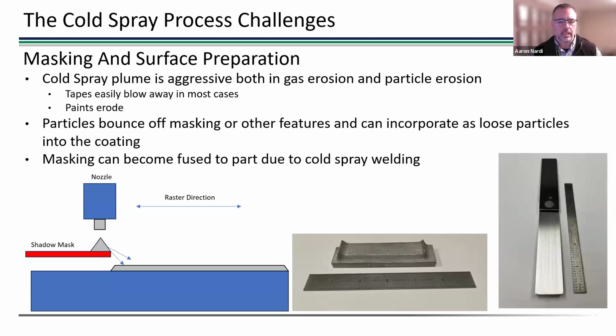And that's really basically what we do. But there's a lot of little nuances to it. So, one thing is you see the little graphic there in the bottom left. When you put a piece of masking close to a substrate, but it's above the substrate like this, for instance, and then you stop once you get onto that mask, you can have deflection issues. What ends up happening is, and it's very material dependent, some materials are sensitive to this, others are not. But if you have deflections off of your mask, you can actually create defects in the first portion of that deposited material.